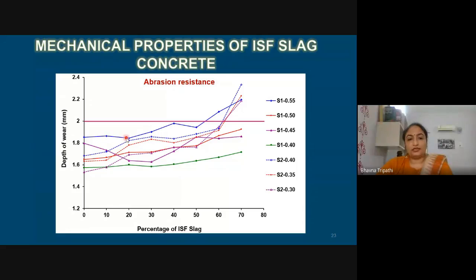But as we increase the slag content, we can see the abrasion resistance decreases. The reason could be that if we compare normal concrete, the conventional concrete, it has sufficient paste. And when we finish the surface of cubes, or when we vibrate the cube, or at site also when we apply vibration to column and beam, the paste comes over upside, and the surface is very much finished. However, in ISF slag concrete mixes, I had already stated that there was some deficiency of paste.